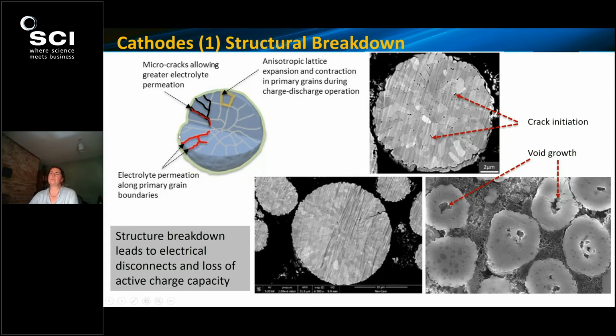But in terms of the operational efficiency, any breakdown in a secondary structure can lead to electrical disconnects between these submicron grains, which will obviously compromise charge transfer and can then lead to loss of active material, which you can see in the bottom right, whereby you get these voids developing where you get disconnections of a lot of the material. So this does literally reduce the capacity of the actual material, which clearly is a dominant aging mechanism.